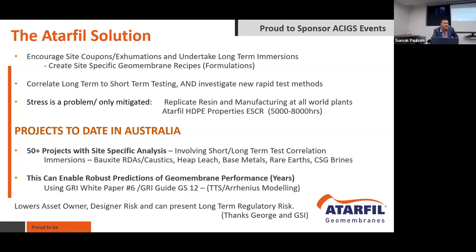Stress is a constant problem. It's very hard to account for. Virtually, eliminate or mitigate is the only option. This is why Atarfil replicate their resins and their manufacturing process around the world. It basically results in HDPE geomembranes with stress cracks in the range of 5,000 to 8,000 hours, which we see as important. It gives us that minimum stress benchmark.